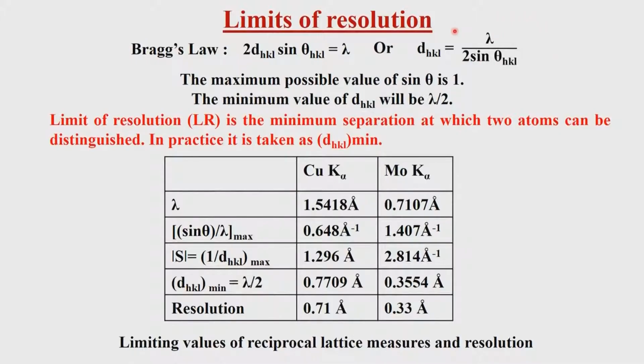What also happens is that in the case of biological molecules particularly, there is a large amount of space which is occupied by what we call solvent water. Mostly it is water in many of the cases in biological molecules. And therefore, this solvent water has some kind of a structure, but not a realistic structure associated with the actual crystal structure of the protein. And therefore, this solvent will give you some kind of diffuseness associated with the diffraction. So much so that even though the crystal is of a very high quality, the extent to which it goes in sin theta is severely limited.